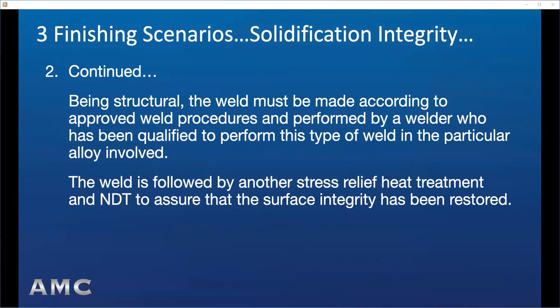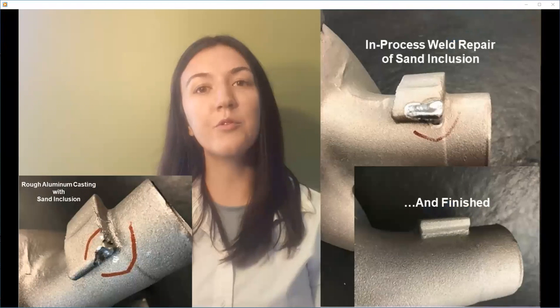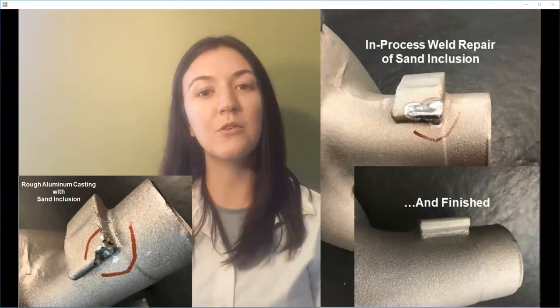Being structural, the weld must be made according to approved weld procedures and performed by a welder who has been qualified to perform this type of weld in the particular alloy involved. The weld is followed by another stress relief heat treatment and dye penetrant or magnetic particle inspection, depending on the metal casting alloy, to assure that surface integrity has been restored. That approval by a qualified inspector is followed by careful surface blending processes Mike described to restore the dimensional tolerance